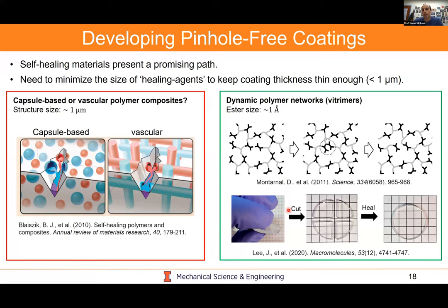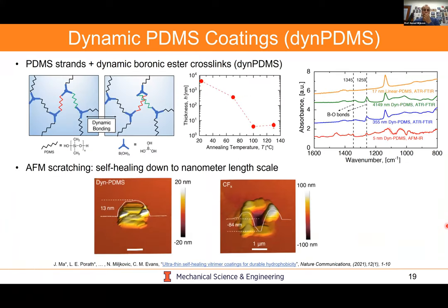So in this case, because of this dynamic bonding that occurs in these PDMS-based formulations, if you were to cut this material, and then if you were just to simply compress it together, it will actually heal and you'll have a perfect material again. And so this to us was very exciting and why we first started this work in collaboration with Chris Evans. So that same student of mine who developed the mechanics of these thin films and durability then went on to actually do some pioneering work thinking about how we could make these dynamic PDMS strands, inject them with dynamic boronic ester crosslinks, and really make them into very fine 10 to 100 nanometer thin coatings.